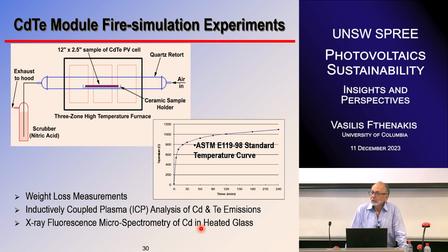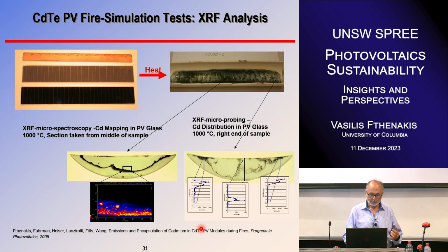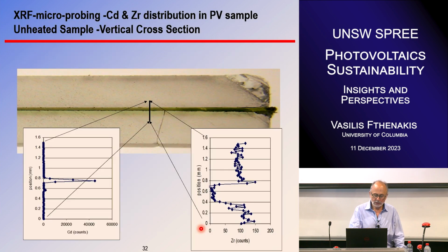For analyzing cadmium and tellurium emissions, we used X-ray fluorescence microspectroscopy at Brookhaven National Lab. What we saw there is that we actually have a small loss of cadmium, as was quantified with the scrubber and the ICP analysis of the scrubber liquids. What we see is that this happened before the glasses fused together.